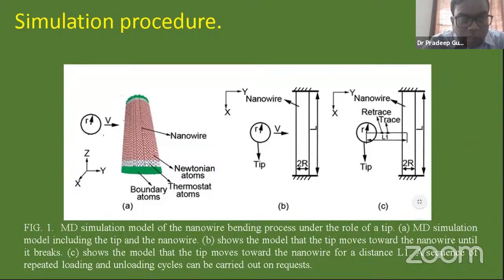We are applying a certain distance with a certain force. The loading rate is already given, ranging from 0.8 to 1.5 angstrom per picosecond, and it is cyclic in nature. We will go to around 10 angstrom, then again increase the indentation depth. First we load the nanowire, and after that we go for the unloading condition. This will continue for around 5 cycles, so that we can see how the nanowire is going to respond.